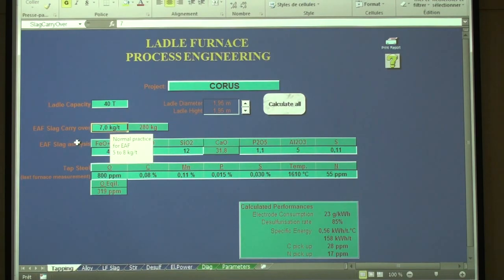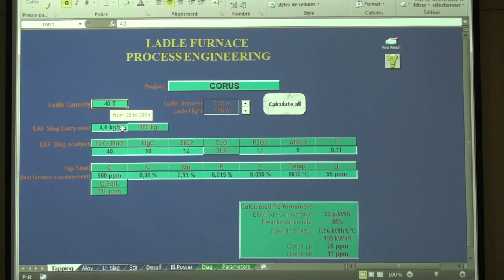So here I have the EAF carryover. It means for this capacity, 4 kilograms per ton means 160 kilograms of slag. Of course, if you have 150 ton, this is 600 kg. And this is the EAF slag analysis. This is the carryover slag from the furnace tapped into the ladle, inside of the EAF. This is not the slag you get on top of the ladle after tapping, because you put lime in the ladle already during tapping. But this is calculated later.